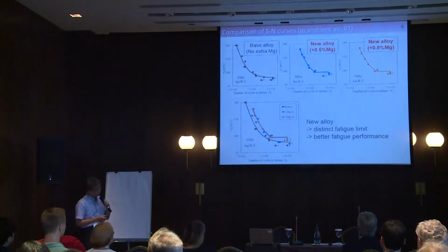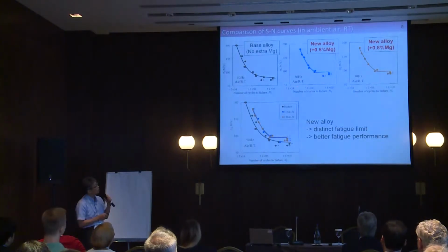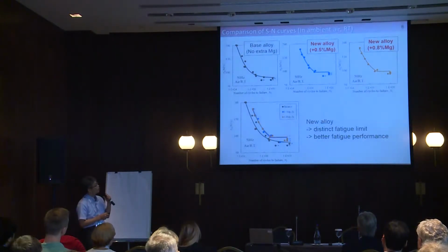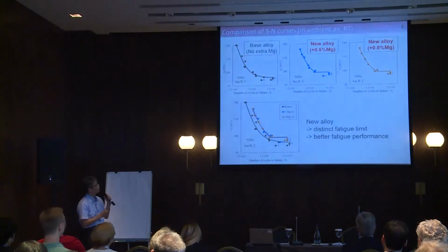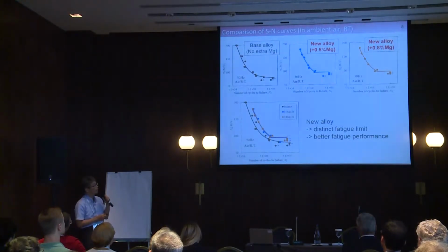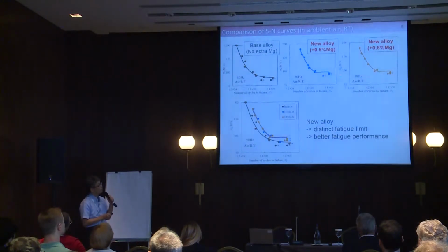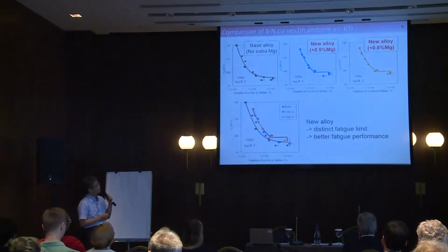Okay, this data shows the fatigue behavior in ambient air at room temperature. The SN behavior of base alloy, again, shows smooth behavior. So it is one of the typical non-ferrous alloys. On the other hand, the new alloys show a distinct fatigue limit here. And when these curves are compared together, the new alloy shows excellent fatigue behavior compared to the base alloy.